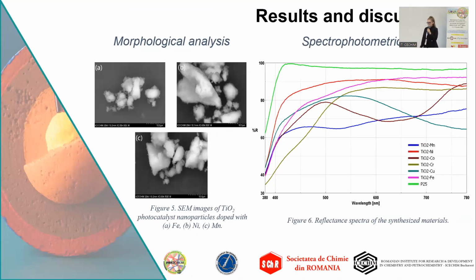In terms of results and discussion, Figure 5 presents some images of titanium dioxide photocatalyst nanoparticles doped with iron, nickel, and manganese, which have been used to test the photocatalytic performance. The photocatalytic nanoparticles formed are highly agglomerated, and also they are visible as spherical shaped particles and clumped distributions. As for spectrophotometric analysis, Figure 6 presents reflectance spectra of the synthesized materials, which present the absorbance of metal oxide photocatalyst in visible area, while titanium dioxide presents absorbance only in UV area.